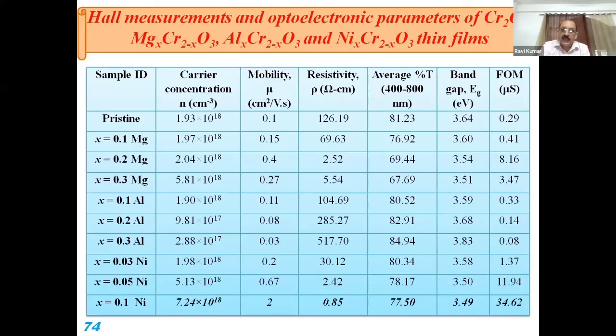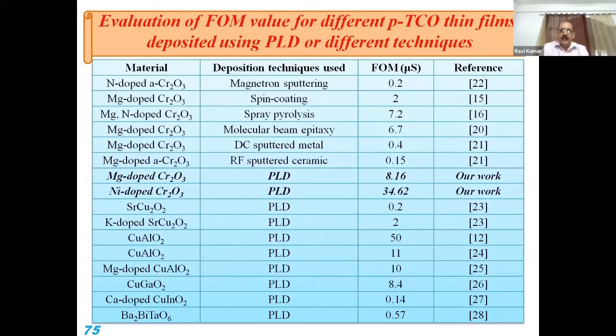Now, if you compare with similar kinds of materials in the literature, what they have achieved so far. We have looked at the literature, and many people have got figures of merit, and our work is showing 8.16 and 34.62 in the case of nickel, which is much higher than most. Only one group, copper aluminum oxide, had a better one than ours, but otherwise this new kind of material which we prepared is showing a better figure of merit.